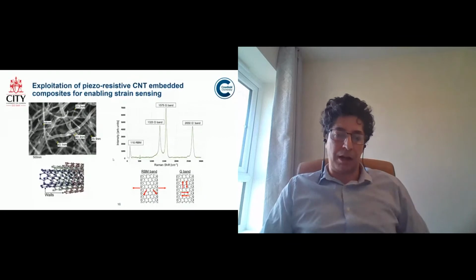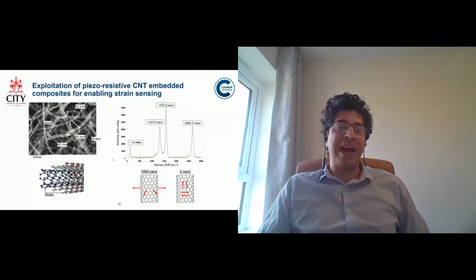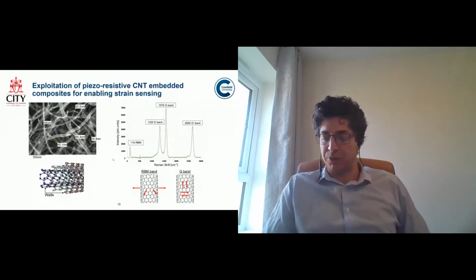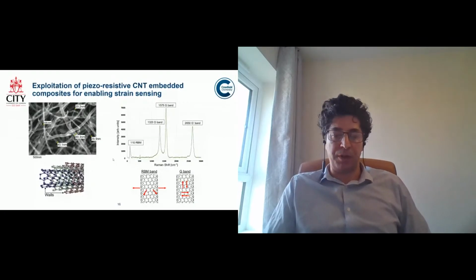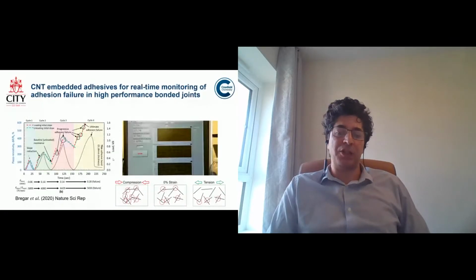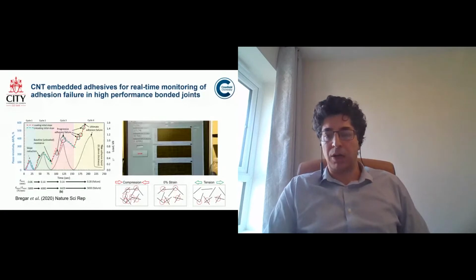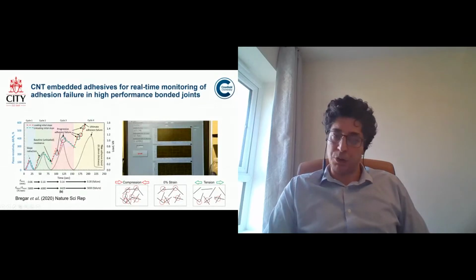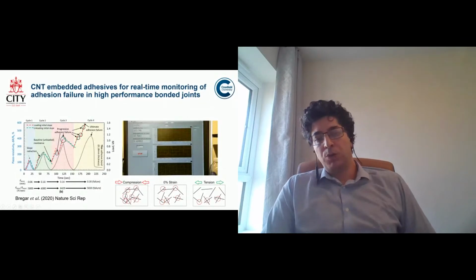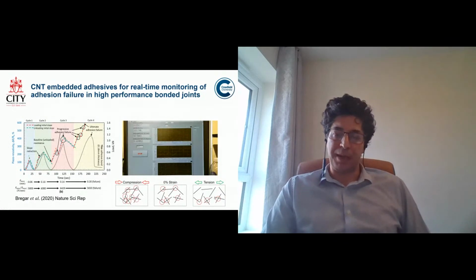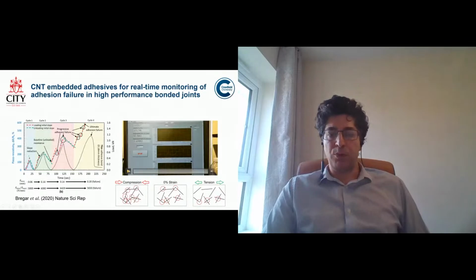We're very pleased to say that after some years of research on enabling adhesion failure sensing in composite assemblies for aerospace structures, we came up with this not too bad publication in Scientific Reports, and you would be able to see lots of innovation in there. But the matter we wanted to report is that we can interpret using the very well-known contact point method that you see at the bottom right, the carbon nanotube contact points. When they lose contact or establish new contacts, you can rely upon that and have an interpretation of adhesion failure. But we see the challenge in a second.